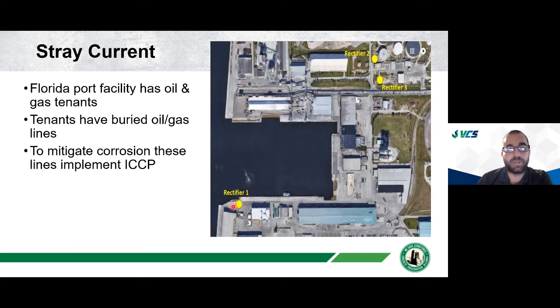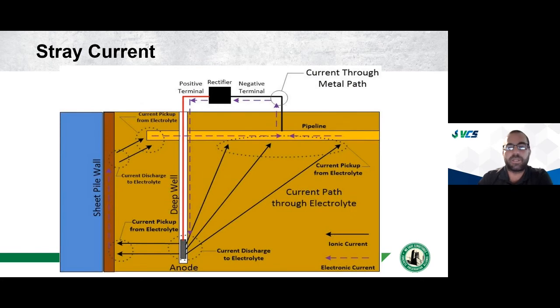Because of the current they were pumping out of this rectifier, I believe, if I recall correctly, they're pushing like 20, 30 amps of current out of it. That's a significant amount of current that can cause a real significant amount of damage on that wall. And so this is a stray current evaluation. We identified that, and if you cause stray current damage on a structure, you're responsible financially for those repairs. And so the port could go to the oil and gas tenant for reimbursement for those walls.